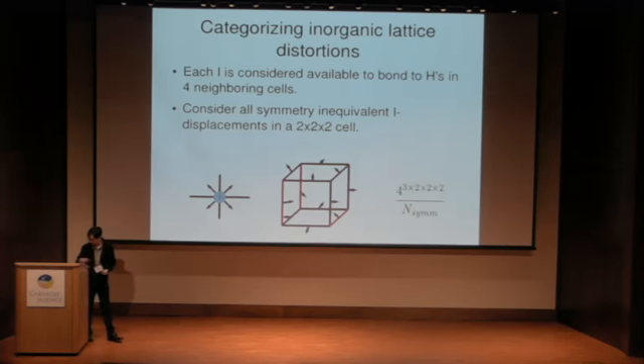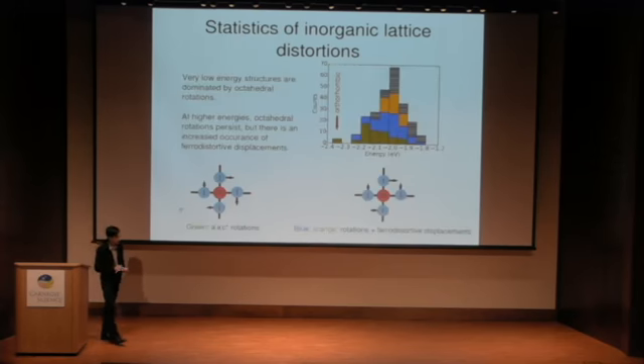And it turns out that even so, there are still only a dominance of a few types of bonding patterns. Basically 2 or 3 types. If you look at the most prevalent ones, the most stable one is the a-minus c-plus rotation. It's coming in the orthorhombic phase, and it's completely dominant in that phase. The other types of distortion patterns are not purely rotations. They contain some sort of ferrodistortive modes. And those are the blue and orange ones. And there are also somewhat more different types of distortion modes, which include ferrodistortive displacements, especially at higher energies.